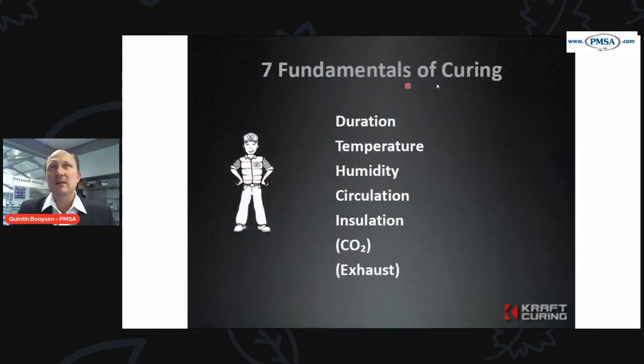So the 7 fundamentals of concrete curing. The duration: the longer we can cure, the better. The temperature: the higher the temperature, generally better, although we don't like to go over around 40 to 50 degrees Celsius. You're spending a lot of money for less significant strength gain, and you could even be introducing thermal cracking. So around 40 degrees is sort of the peak temperature that we use in brick, block, and other forms of concrete, although some people do push it up a little bit higher. But in our experience, over 40, you start wasting money. You're putting in more heat than the ultimate benefit that you're getting.